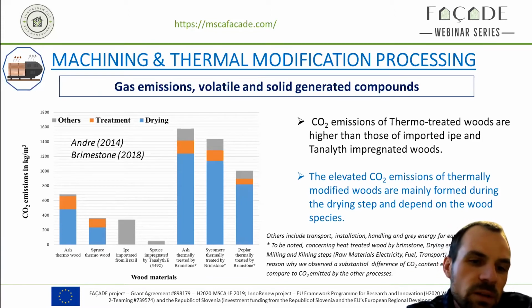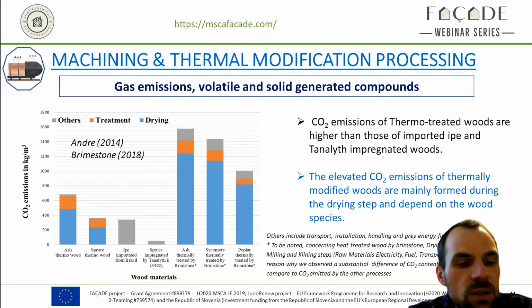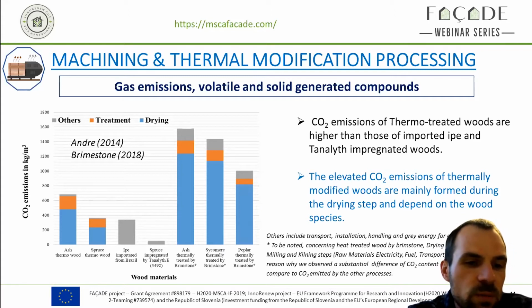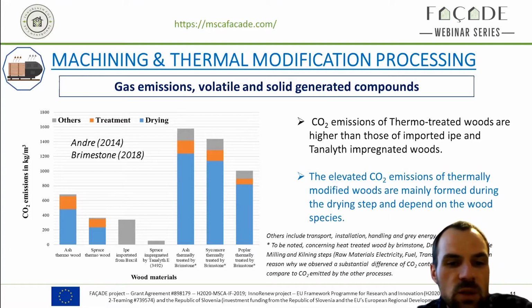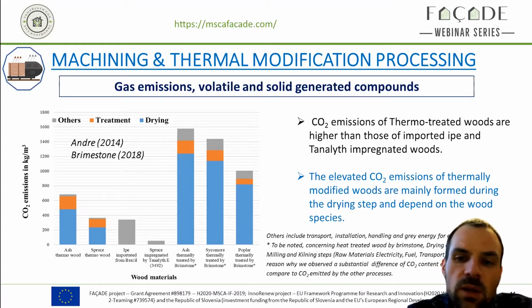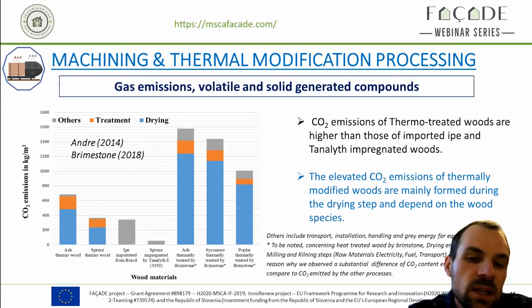Now we have a graph which presents CO2 emission for different treated woods. So we find again the ash and spruce treated by thermal wood process, IPE imported from Brazil, and spruce impregnated with tanalite. These results come from the study from Andre. And on the right, the three thermally treated woods are the results from the Brimstone studies, the Brimstone company, and concern the ash, sycamore, and poplar heat-treated wood. We need to pay attention because the drying step from the Brimstone company includes additional operations such as milling and kilning during the drying steps. So it is for this reason that we can observe a higher CO2 emission from the Brimstone company than those from Andre's studies.